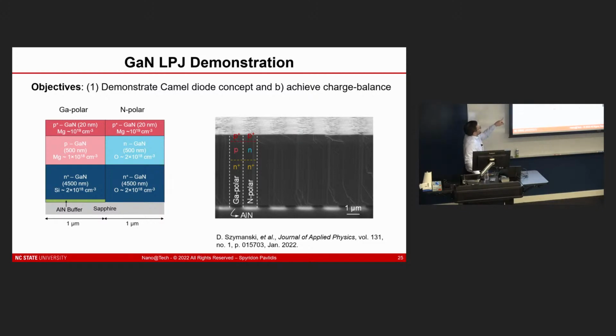Yeah. Keep in mind that current will flow following the lowest barrier, right? These PN junctions have large barriers between them. With GaN, you'll have a 3.4 eV barrier there that you have to surmount. This is designed, this is the camel diode, so this is a little bit of an exception because it's thin and we're depleting it. But after it climbs through that, it's going to go through the lower barrier pathway, which is down here. So we don't use the gallium polar or this P-type region for conduction. We use this to balance charge, which gives you that difference in E-field distribution, which then leads you to have lower conduction losses in the superjunction structure.